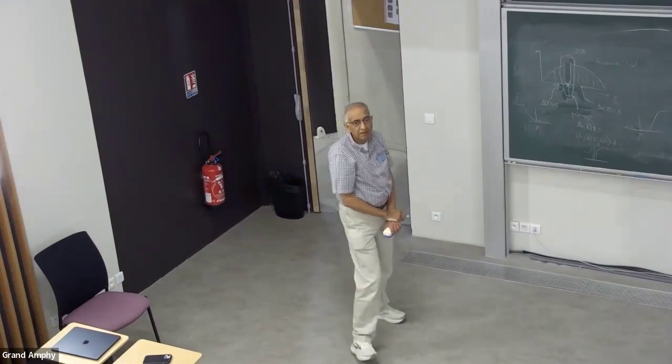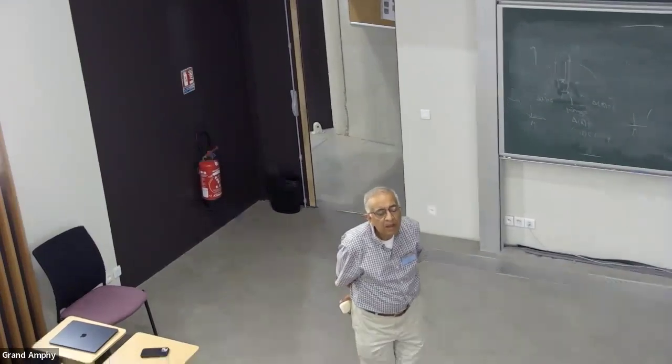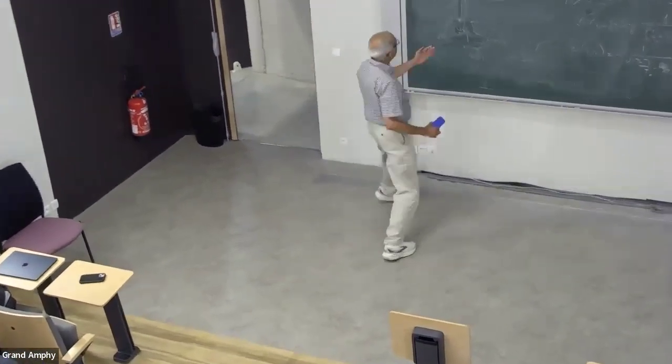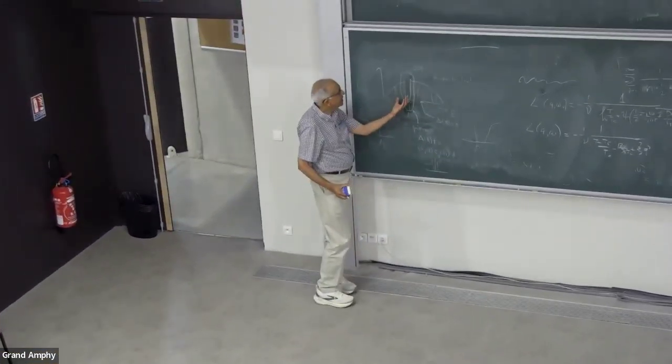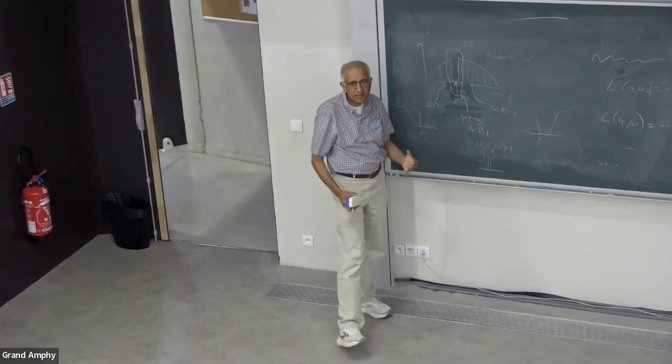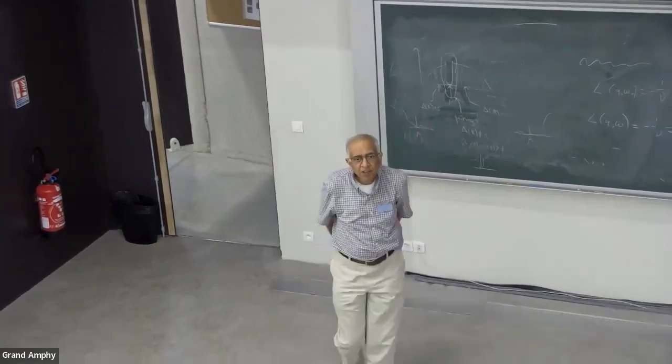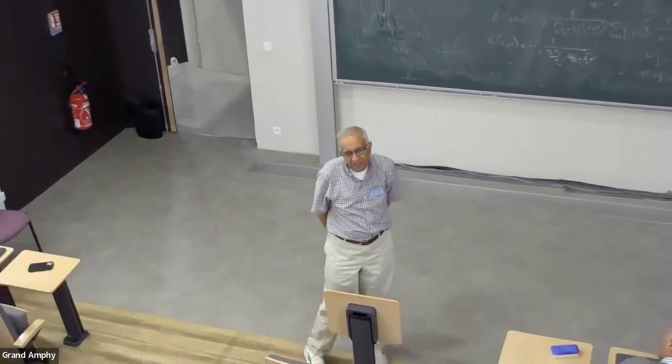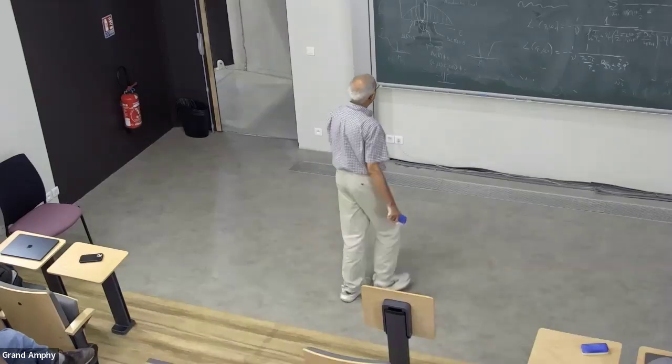I don't quite understand what you mean by here. Okay. The point is what states lie low down in energy in an Anderson insulator? Those which are in deep valleys, very low energies. So you already have 2 electrons in there. You can't really make electron hole pairs there.